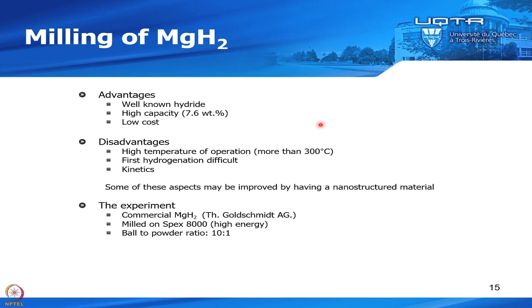Magnesium hydride is a well-known hydride. It has a high capacity, 7.6 weight percent, and it's relatively low cost because it's abundant in the earth's crust. The disadvantage is that it has a high temperature of operation, more than 300 degrees C. Usually the first hydrogenation is very difficult, and also the kinetics are relatively slow.